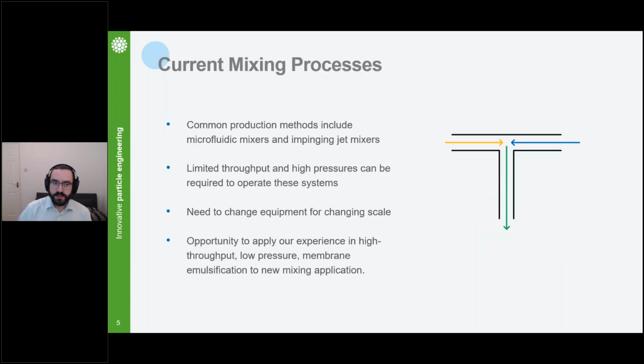A lot of the current processes are based on microfluidic mixers and impinging jets, my crude interpretation of one on the right there. Essentially we're just blasting two jets together, and then the resulting solution is where that solvent is diffusing into the aqueous phase and we're forming those particles. Some of these systems can have quite limited throughputs, especially in the case of microfluidic systems, good on the small scale, not so much on the large scale. So that gets into difficulties if you're trying to make lipid nanoparticles for a few million people, say.